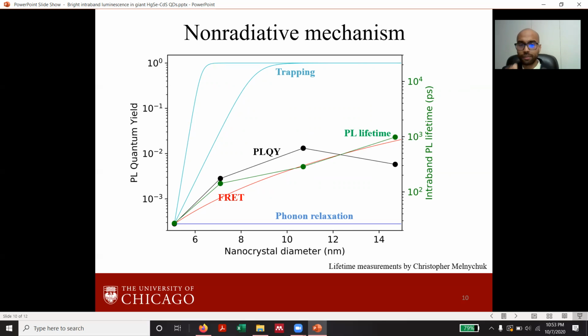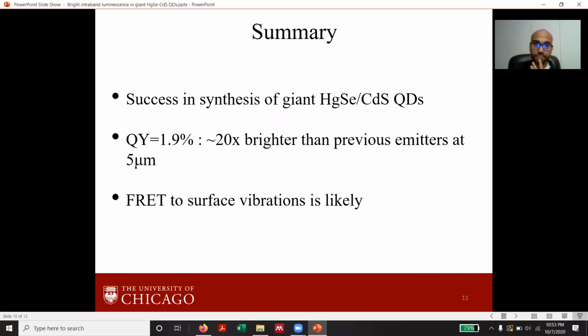Apart from fundamental interest, this understanding of the mechanism has a lot of practical applications because the performance of quantum dot infrared detectors is limited by the fast non-radiative decay. And the understanding of this mechanism shows that the direction for improvement of the detectors is clear. We need a clean method to do a surface exchange of the high frequency vibrations and do a ligand exchange to give ligands which don't absorb in the mid-infrared.